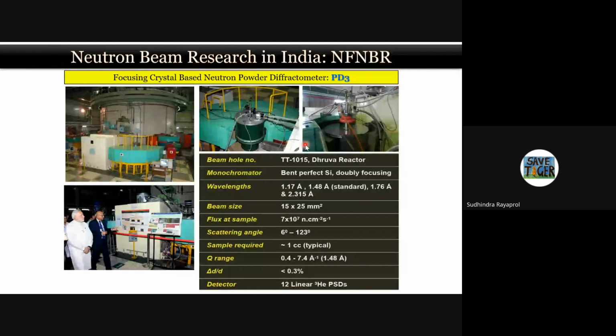For collecting one typical set of diffraction data, which means you collect one pattern of diffraction data, for one sample it takes about 2 to 3 hours to get good data which is refinable. So if you want to do it as a function of temperature and field, the time adds up like that. If you want 10 temperatures, it will take something like 20-24 hours for one sample. So it is like that.